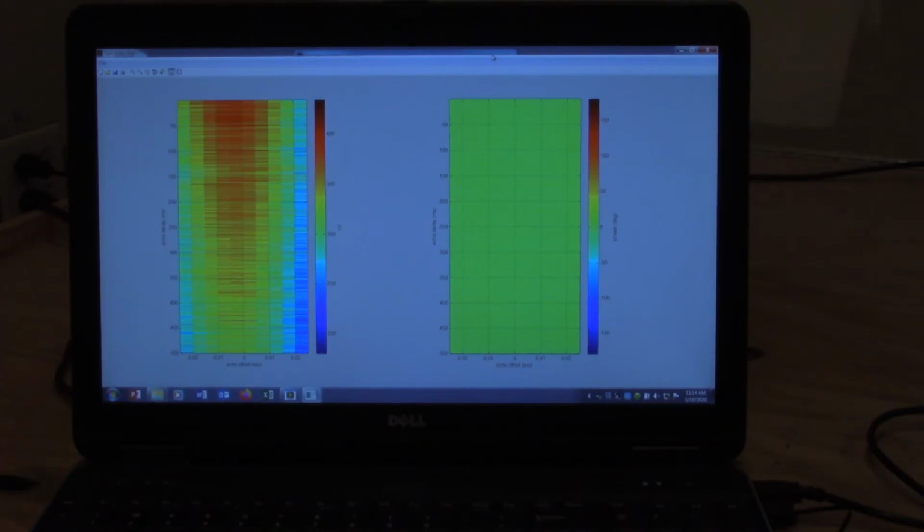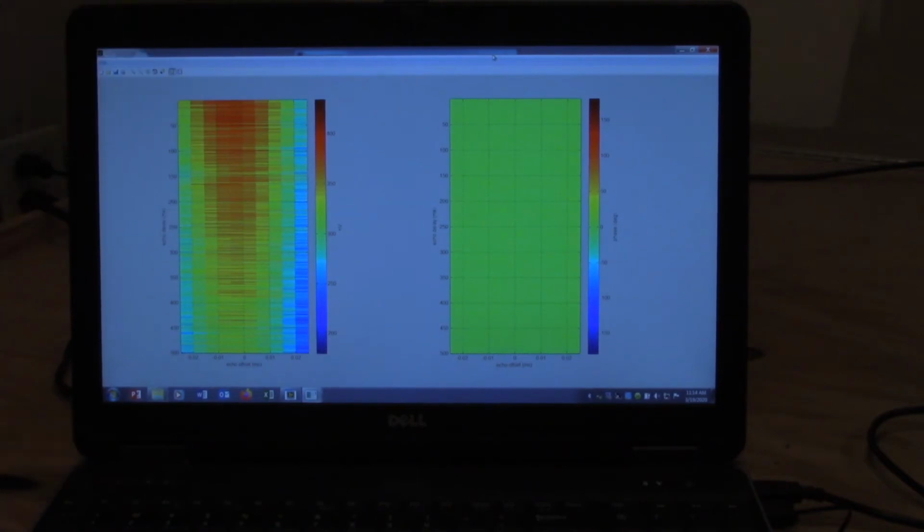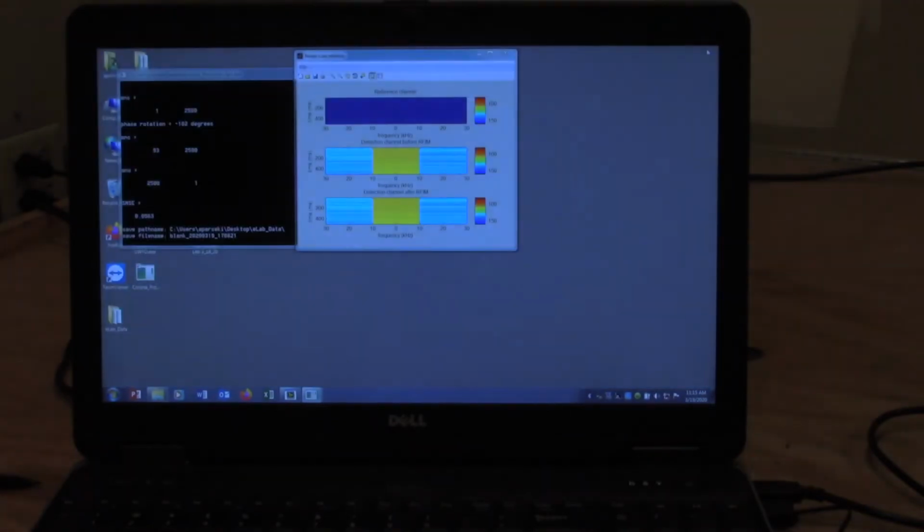The next image is showing all of the echoes from the CPMG reorganized here in a vertical stack. And what we're expecting is this sort of flame shape. This flame is really long because it's just water. If you're looking at a sand sample, it's going to be shorter. The center of this is what was extracted to make the exponential relaxation curve, the envelope of all those echoes. The other side is basically a data quality check. It's looking at the phase offset, and we want to see this as all green, meaning there's no phase offset in the sample. If there is any noise in this, it's usually where there's no water or low water content. So this window is mostly QAQC.